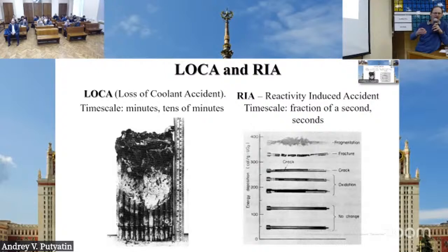The fuel pellet might have touched the cladding, but for a very short time without very strong consequences. If you have larger energy release, the fuel cracks, and finally the fuel may fragment completely. And of course, it turns out it blows out the cladding.